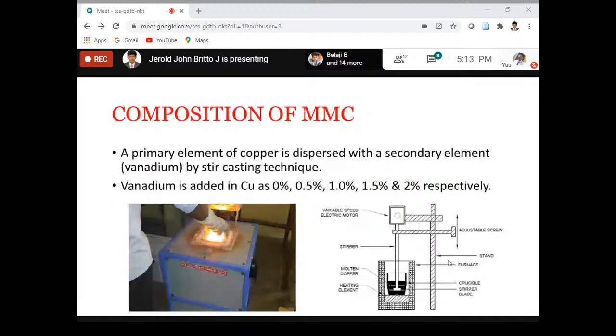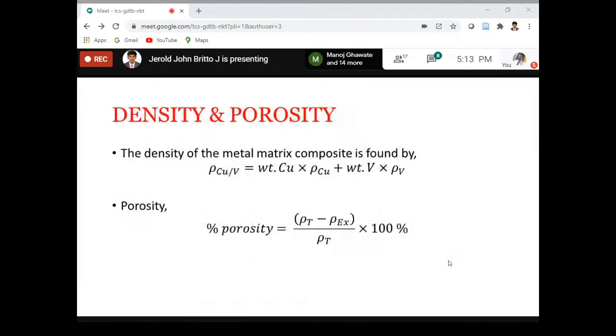As I already told, stir casting is one of the most economical methods, so I have used the stir casting method to make this component. In this, copper is initially filled in a furnace. The furnace is heated to about 1200 degrees centigrade, and vanadium is slowly added to it at a fixed rate. By varying the percentage of vanadium, different composite samples were made. After producing the samples, I tested the density and also the porosity.